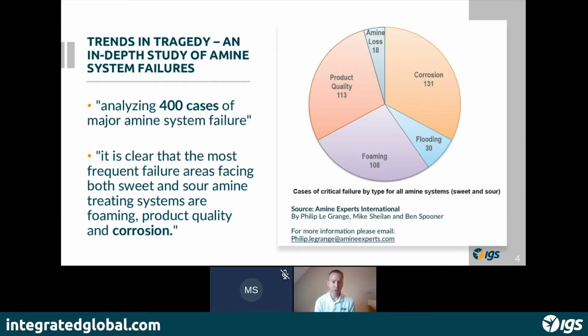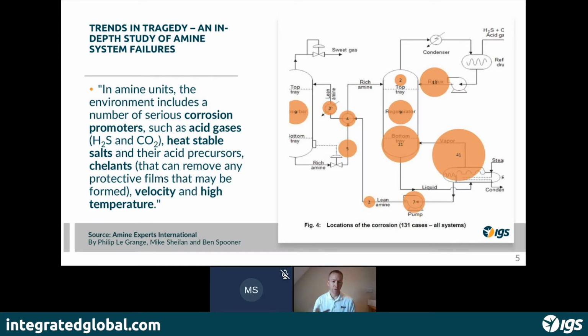And what was very clear was that corrosion was a major factor when we looked at amine system failures. And despite the fact that a perfectly designed system with the right materials incorporated shouldn't corrode from new, or if operating under design parameters, that is clearly very difficult to maintain in a real life situation. And amine systems in particular have many different areas inside them that create challenging environments from a corrosion perspective. So as well as reviewing the different cases, they also had a look at where these were located in an amine system. And what we see is a fairly general overview here of the locations where the corrosion challenges were taking place. And what we can see is there's different areas of the plant that face different issues.